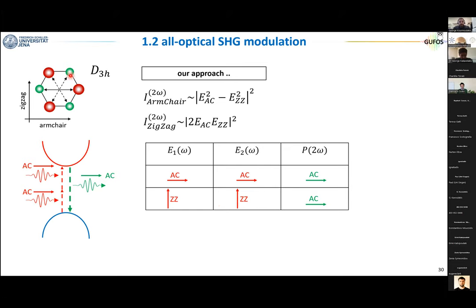Now, I should tell that if you look at this hexagon in TMDs, you can assign it to the so-called D3h point group or crystal symmetry. I don't go into the details, I only focus on the fact that there is a high symmetric direction, the one that connects the metal atom to the chalcogen atoms. This is the so-called armchair direction. And of course, you can rotate this hexagon by angles of 120 degrees, that is 2π/3. This is the reason for the 3 in this letter number here. So if you divide by 120, you always end up in the same symmetry. So there is clearly a symmetry operation, a 120 degrees rotation, that brings me into the same condition.